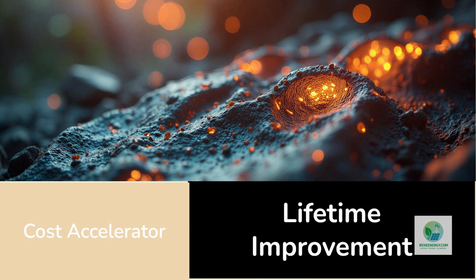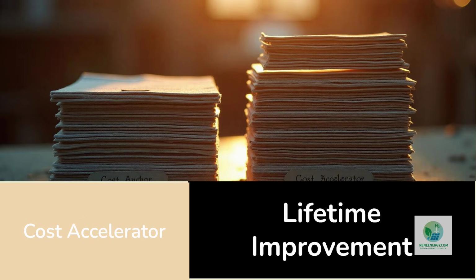Even more remarkable is the lifetime improvement. Nano-reinforced membranes with engineered sidechains have demonstrated lifetimes of 20,000 to 40,000 hours, double or quadruple the lifetime of traditional membranes. Lifetime matters. If a membrane that previously lasted 8,000 hours now lasts 32,000 hours, the cost per kilogram of hydrogen produced drops dramatically. When combined with reduced material cost, the effective improvement is close to 10x. Membranes, once a cost anchor, are becoming a cost accelerator.